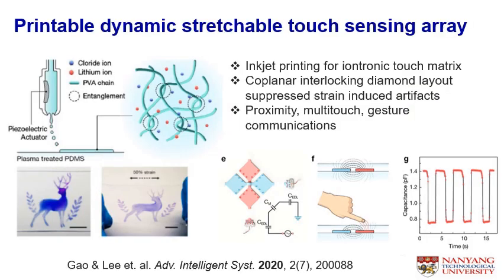Apart from 3D printing, we also utilize inkjet printing of hydrogel to create an iontronic touch matrix. In this work, we demonstrate a formulated inkjet printable ink and use the inkjet printing to create a coplanar interlocking diamond layout structure in order to suppress the strain-induced artifacts during dynamic touch sensing. The design allows the proximity sensing to be achieved, multiple touch, as well as gesture communication.